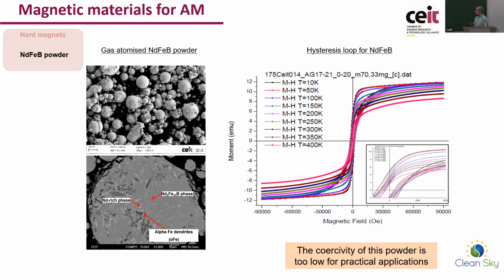There are two reasons for that. The first one, well, this is the microstructure of the powder. If you process by additive manufacturing, you are going to melt this powder and you are going to solidify. So the microstructure is going to be different to this, but it's going to exhibit some main characteristics that are going to be equivalent. The first point is, as you see here, there is always some residual alpha iron, which is a soft magnetic phase. And what this causes is that the coercivity of the material is low. Probably this could be corrected by applying an annealing on the material after additive manufacturing processing.